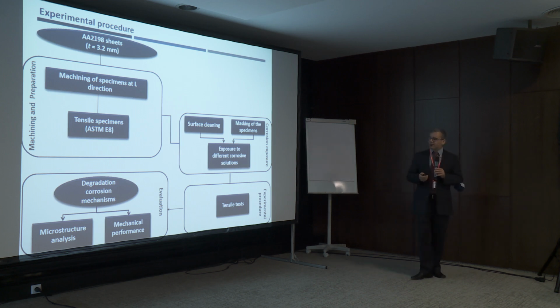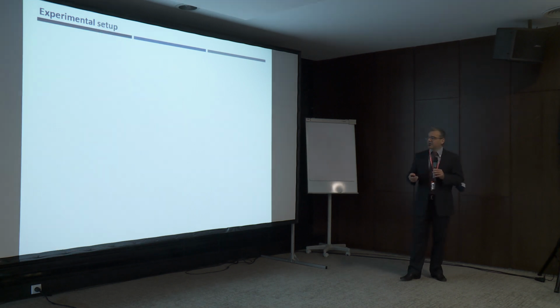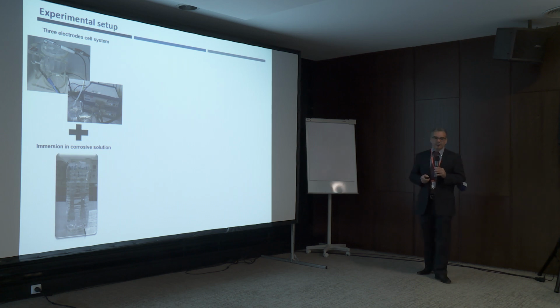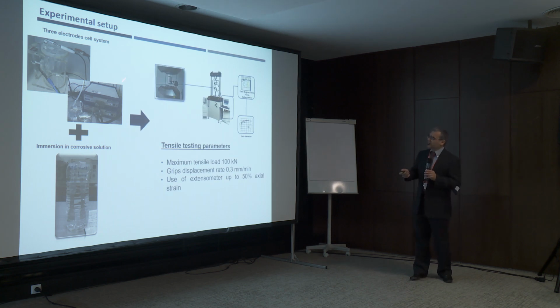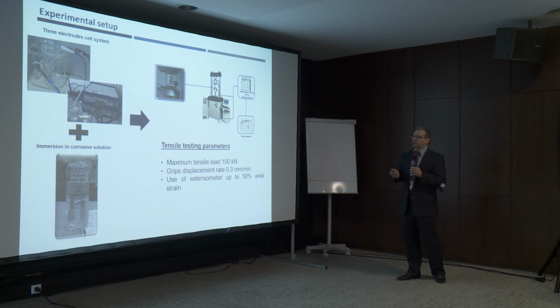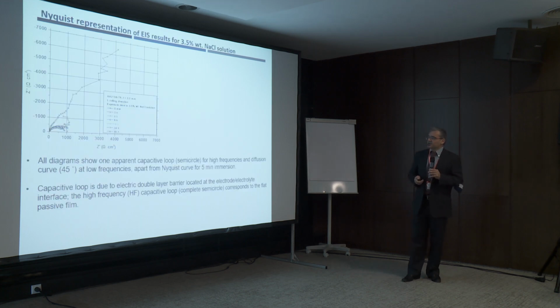So this is the flow diagram. Of course, we machined the tensile specimens, surface cleaned, corroded the specimen, and then performed the tensile test and had an evaluation. Before the mechanical test, we also had some impedance tests, electrochemical tests, just to have an idea of the corrosion susceptibility. Then we perform the test. This is OCP, open circuit potential, typical for electrochemical evaluation. And then the tests were performed at a tensile tester.